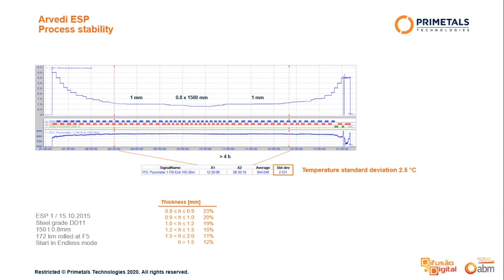The first, the process stability resulting in extremely stable temperatures. The diagram shows a 6-hour sequence where more than 4 hours were produced on a thickness of less than 1 millimeter. And the finishing rolling temperature has a standard deviation of only 2.5 degrees. This means, contrary to coil or batch rolling, we have no temperature fluctuations, and you know always in advance in which position of the plant you have which temperature and which metallurgical conditions. So the process is completely predictable.